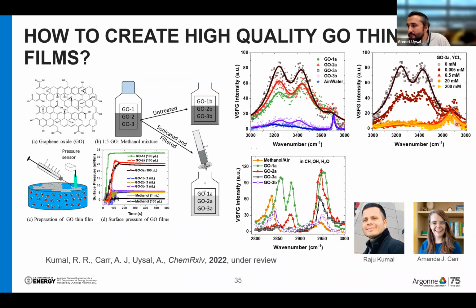And we believe this is some water coordinating directly to graphene oxide or trapped between graphene oxide layers. And this is very important in membrane type applications, because how your ion interacts with your membrane material is also determined by the presence of other water molecules around, and we are showing that there's a persistent water layer on graphene oxide, independent of the ion adsorption. And controlling this water will be very important for membrane applications.